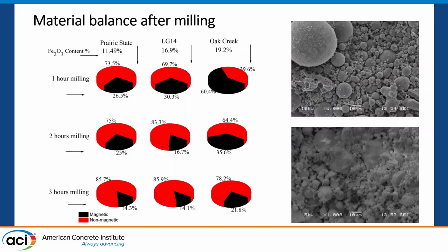And here, initially, even after 1 hour milling, sorry, we had 60% of magnetic particles. So magnetic particles were embedded into the matrix. Upon milling, the quantities are reduced, but the concentration of magnetic particles in this magnetic portion is increased. So this is the reason why we need to mill, and obviously particle size reduction is also very useful for pozzolanic reaction and the reactivity of the particles. Those were really good products at the end, both products were very beneficial.